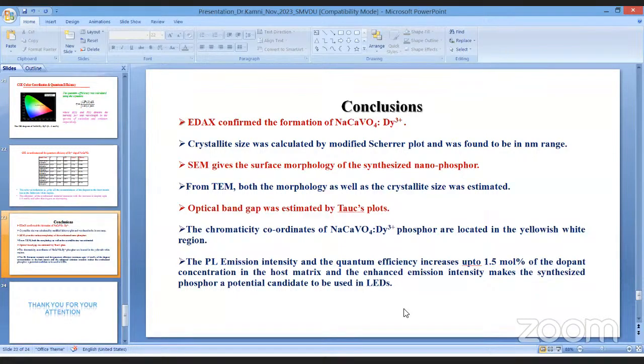Optical band gap was estimated by making use of the Tauc plots, and the chromaticity coordinates were located in the yellowish-white region of the spectra. The PL emission intensity and the quantum efficiency increase up to 1.5 mole% of the dopant concentration in the host material, and the enhanced emission intensity makes the synthesized phosphor a potential candidate to be used in LEDs.